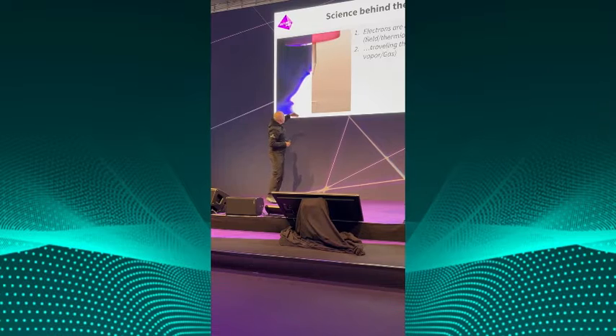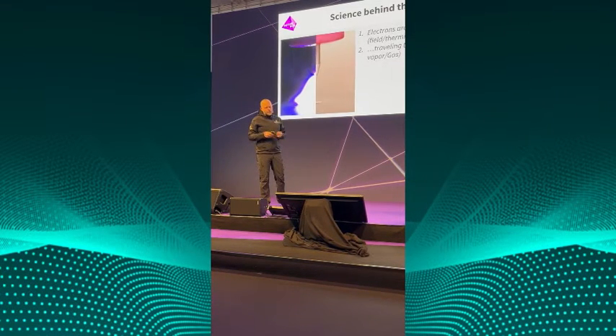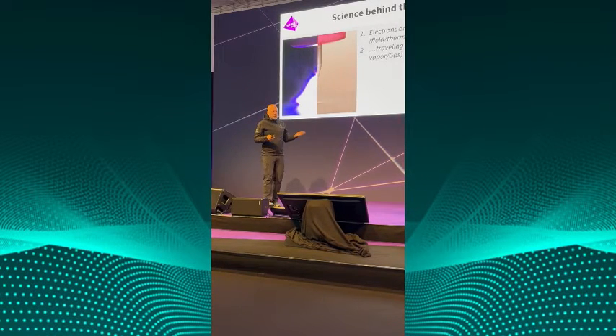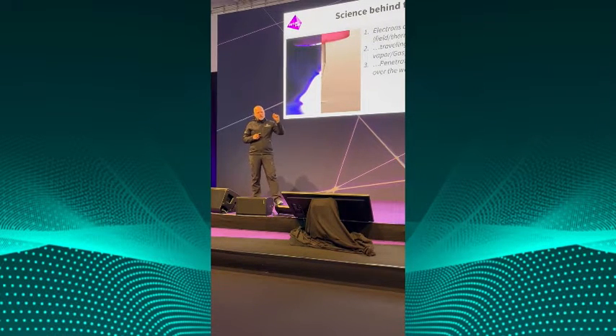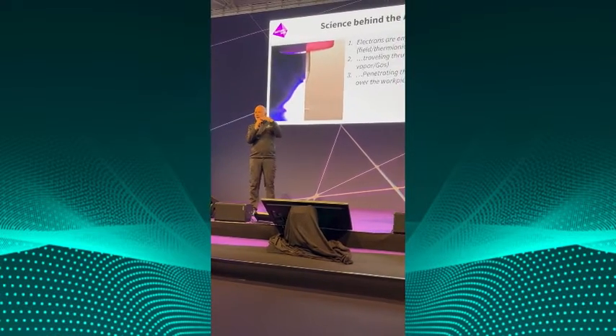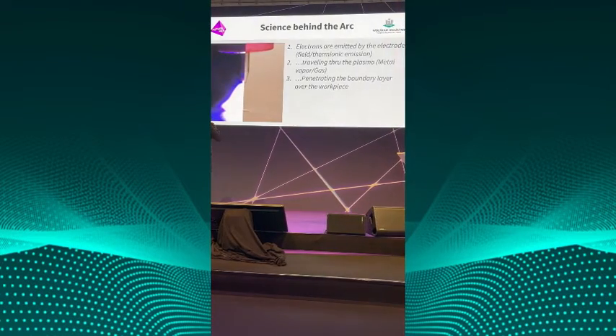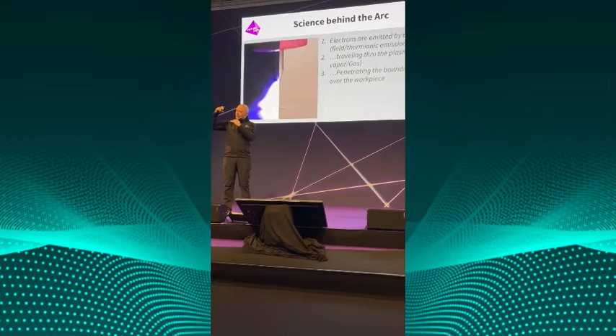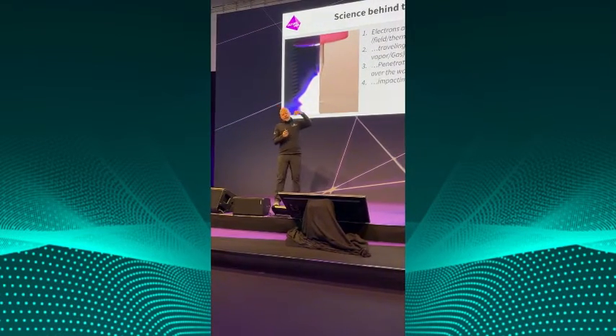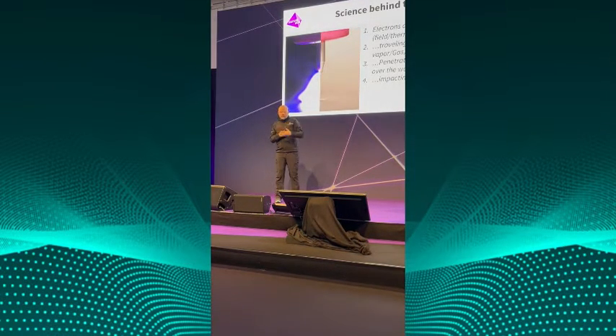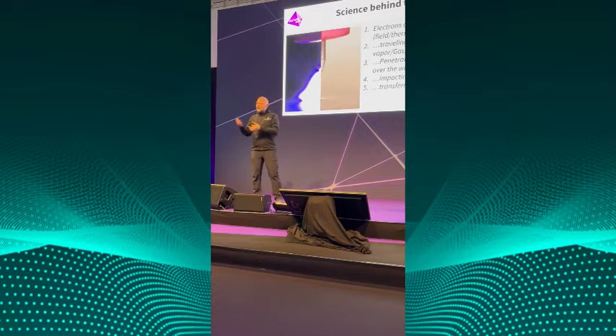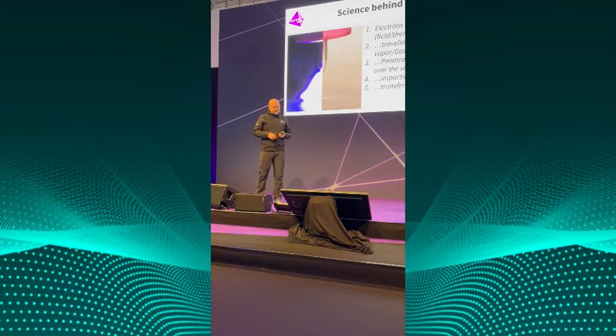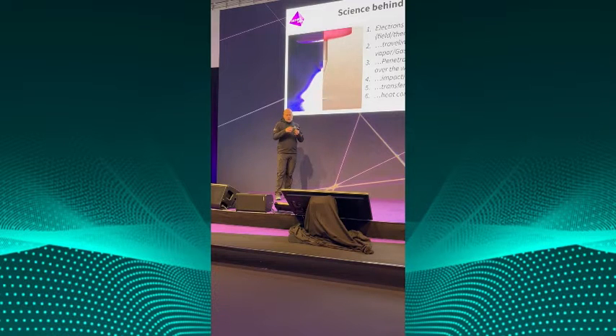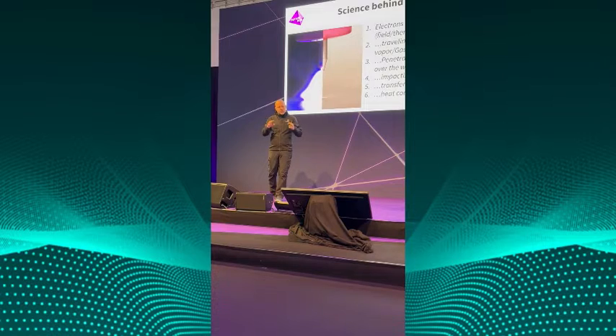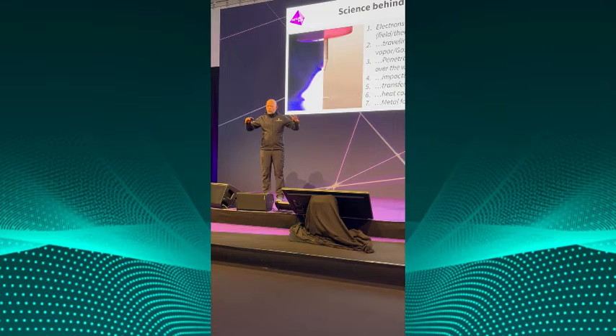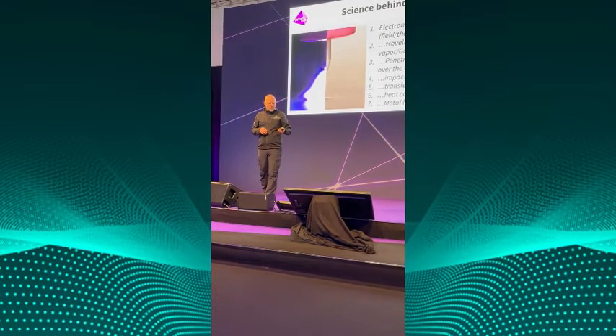It travels through the arc column down towards the weld material or the base material through either gas or metal vapor as soon as you have an established weld puddle. It penetrates a boundary layer, a static layer of plasma over the workpiece, which is about 0.2, 0.4 millimeter thickness, and this is essentially how you transfer the energy from the arc to the workpiece. So the electrons have kinetic energy. They penetrate the boundary layer, impact the base material, and transfer their kinetic energy as thermal energy to the workpiece. The thermal energy is conducted through the metal, metal is a very good conductor, to the weld puddle, and starts to melt or even evaporate the base material.